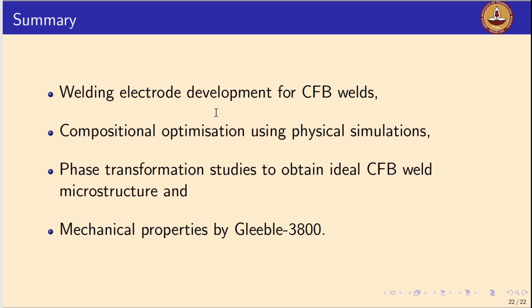Right, so the mechanical properties that we achieved using this exercise are much better than the base material in welds. Right, so we made welds, and the carbide-free bainitic containing microstructures are welded using these electrodes, which we actually optimized from the study, right? So they even showed much better properties than the welds made using austenitic filler.